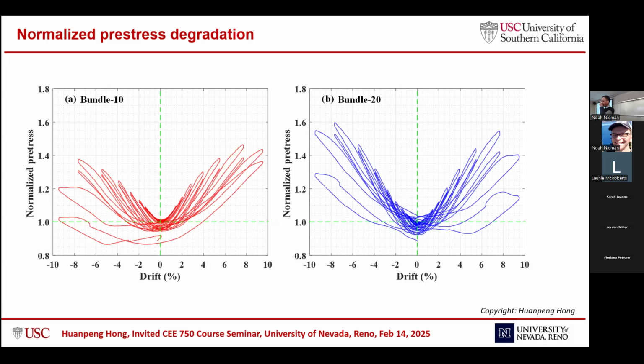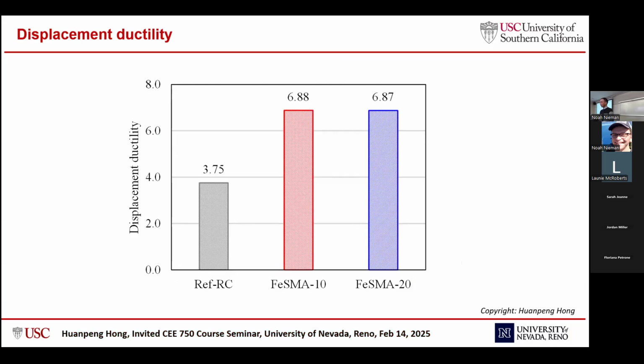And here's the normalized pre-stress degradation. During this test, it is noted that we loaded the column until 9.5%. This is really large drift. And up until the end of the test, both of the columns, the iron SMA bundles in it, remain intact. Until we loaded these columns to 9.5%, the degradation in the pre-stress is less than 15%. Means the post-tensioning is there until the end of the test. So here's a comparison of the displacement ductility. The displacement ductility of these two proposed columns is around 7, and for the conventional RC column it is around 3. So there's a significant improvement of the displacement ductility.